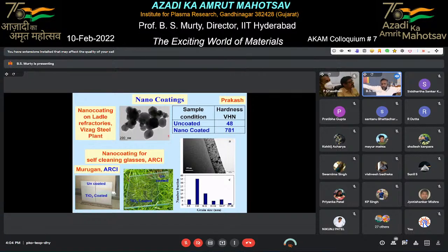For example, in steel plants you have huge ladles where the steel is poured, liquid metal at 1600 degrees centigrade, and the refractory bricks get worn out. We simply coated nanoparticles on the refractory bricks in Vizag steel plant, where the coating gives you almost 800 Vickers hardness, whereas uncoated material has less than 50 Vickers hardness. Because the wear resistance is so high, we were able to demonstrate that the life of the refractory bricks can be doubled without much effort. You need just about a 10 micron coating. That's it, nothing beyond that.